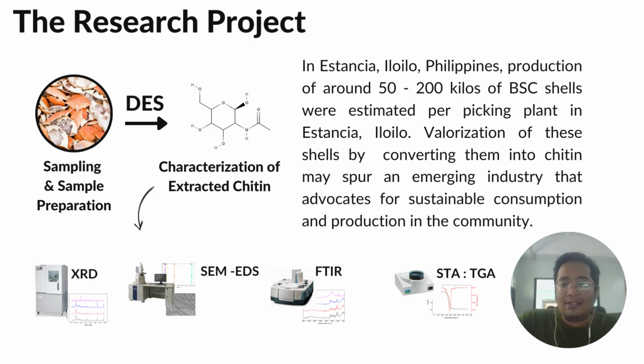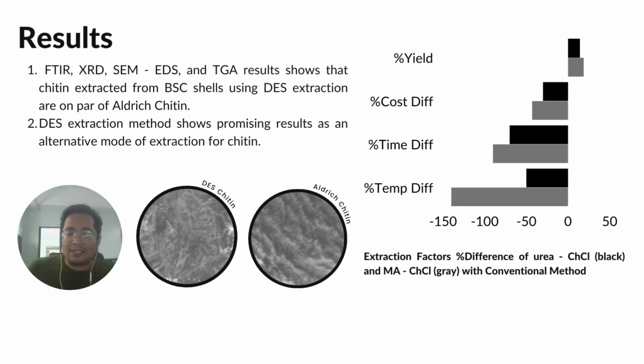Shells of these crabs were then processed into chitin using the aforementioned deep eutectic solvent and characterized using XRD, SEM-EDS, FTIR, and TGA. For the results, the characterization techniques showed that the chitin extracted from the blue swimming crab shells using the deep eutectic solvent extraction is on par with the Aldrich chitin. The deep eutectic solvent extraction method shows promising results as an alternative mode of extraction for chitin in terms of yield, cost, time, and energy consumption, as seen in the figure where the extraction factors' percent difference of urea choline chloride in black and malonic acid choline chloride in gray are compared with the conventional method.